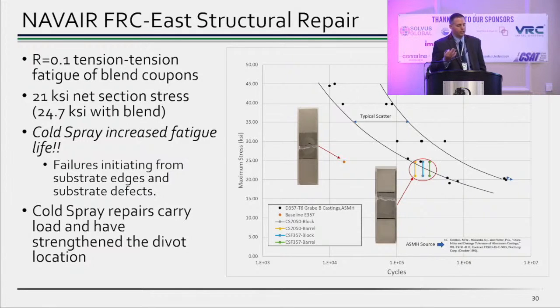So in fact, we are seeing structural load carrying capability out of the material. Now I have these drawn as lines, the yellow and the blue and so forth, because if you actually consider that we're carrying load, then the stress level is really only 21 KSI as opposed to 25 KSI. So we're not quite at the scatter band if you consider it as 21 KSI, but the fact is we're failing from defects in the substrate, not from the coating. And that's what's important here. The substrate is the limiting factor, not the cold spray material anymore. So we have a full structural capability out of these coupons.